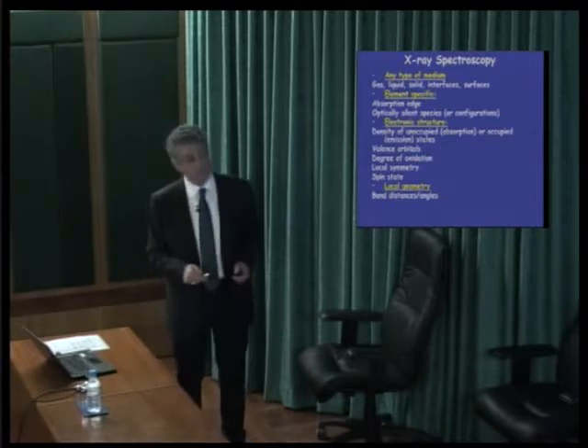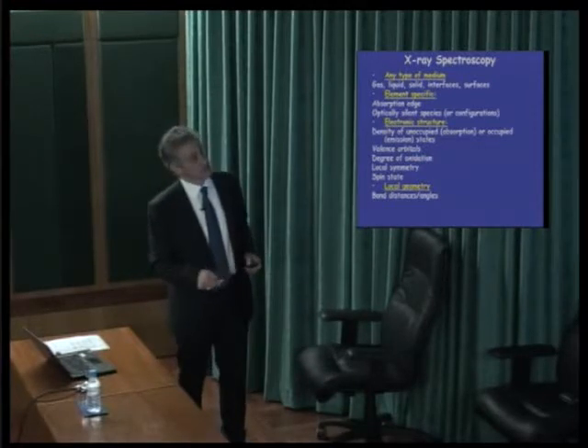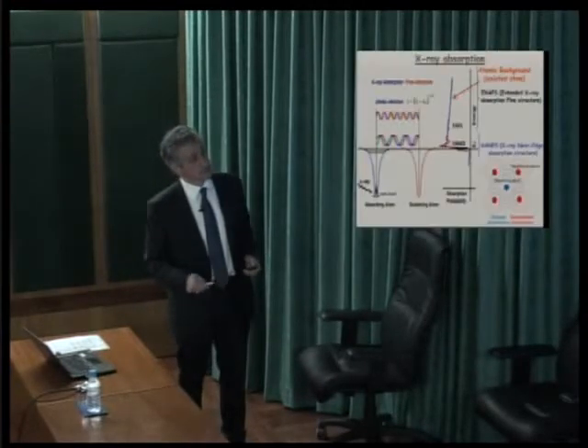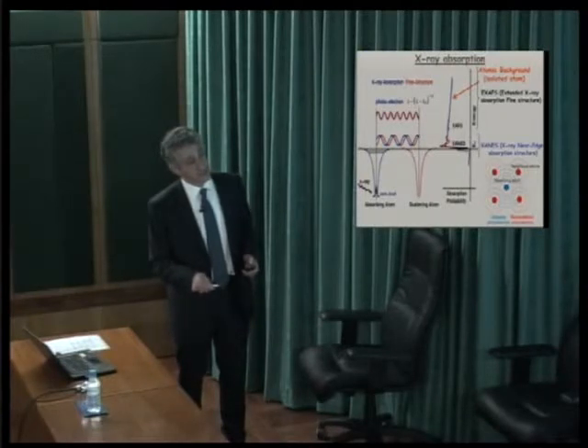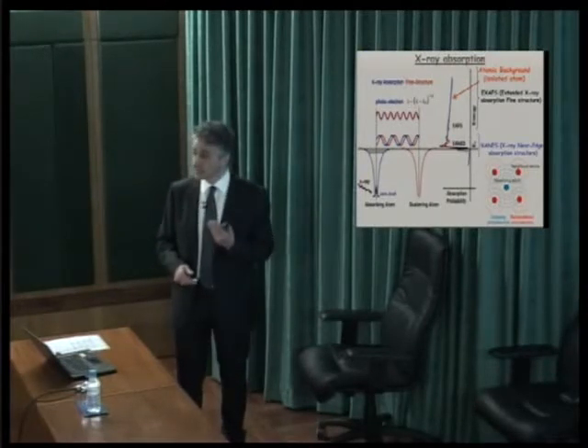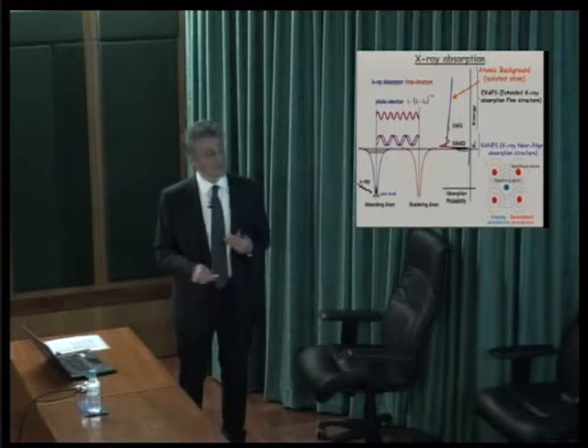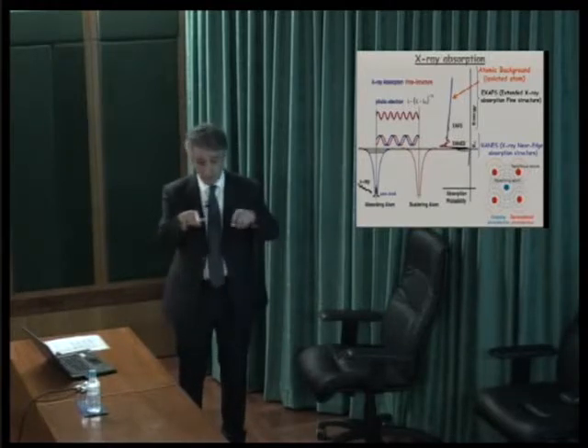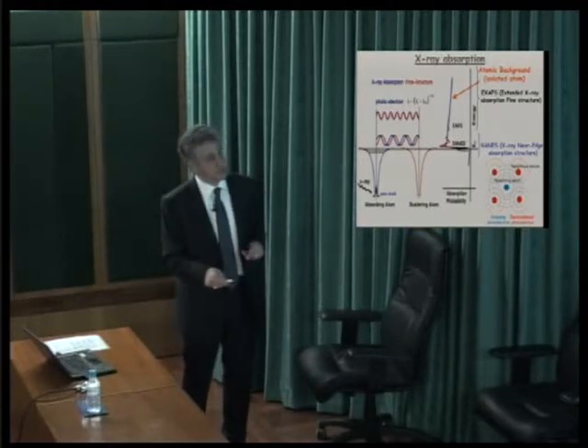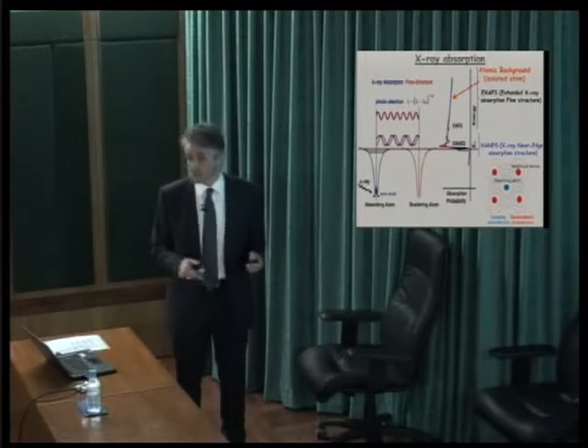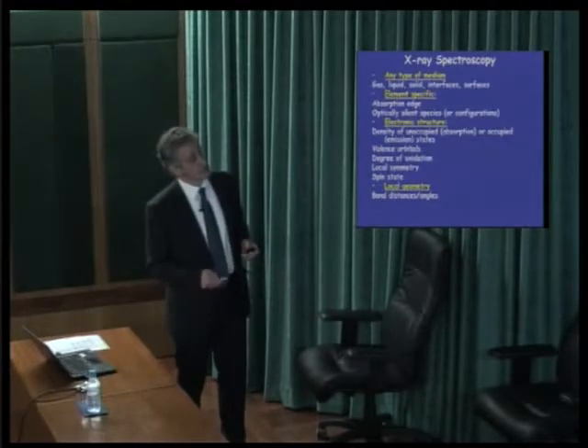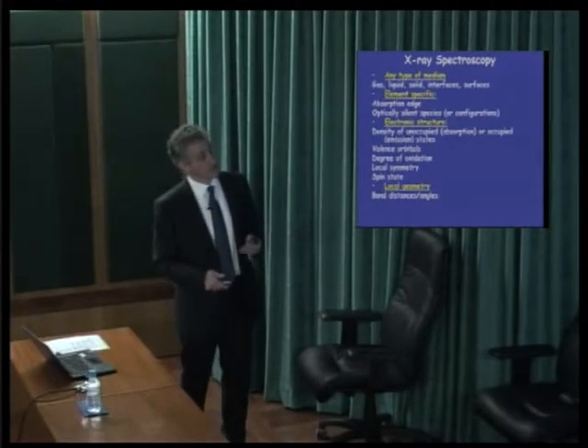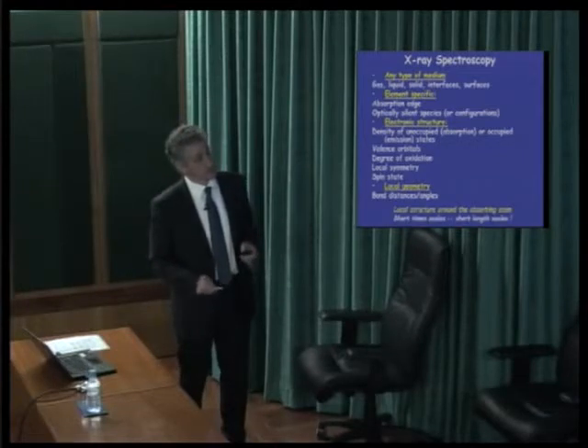You can apply it to any medium. You are element specific. You get the electronic structure because you can see these transitions. By the way, these are valence orbitals. And if you do something to the system, you read off directly in the spectrum what has happened via these transitions. So they're very useful: density of state, oxidation state, and so on. And then you can get the bond distances and angles.